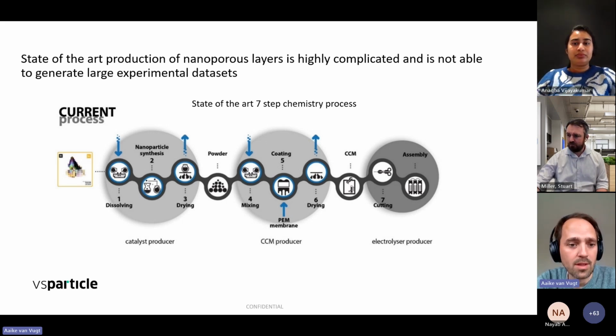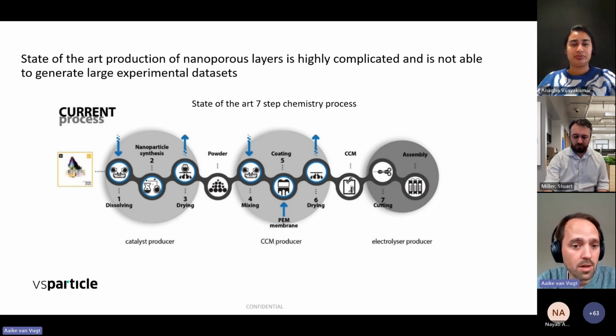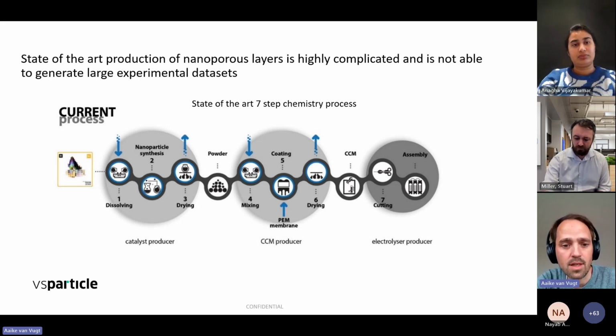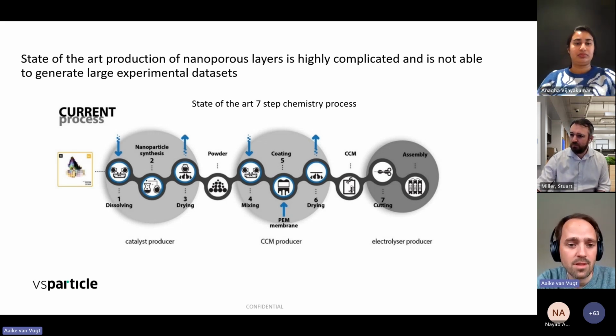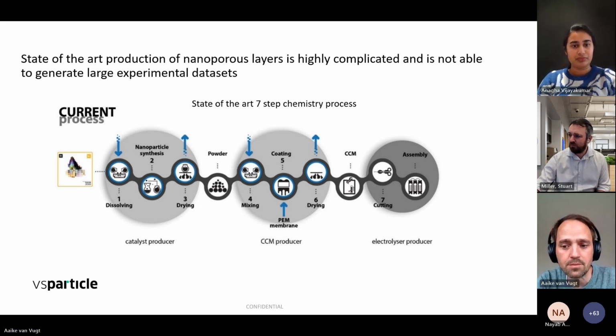So you start with wet chemical synthesis of your powder, which is a time-consuming, complicated process. And then the second step is you do a wet coating process. So you mix your powder again with all kinds of chemicals to slot die coat it onto your surface, and then you put it into the oven to evaporate all the chemicals. And then after a 7-step process, you end up with some kind of porous structure being glued to your substrate.